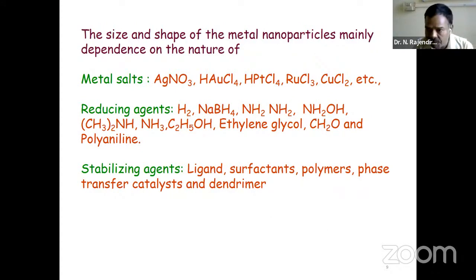And in the chemical methods, there are three constituents mainly required. That is the metal salt, reducing reagent, and stabilizing reagent. Normally, if you want to prepare silver nanoparticles, you have to take silver nitrate or silver chloride. For gold nanoparticles, auric chloride; for platinum, ruthenium, the respective metal salts we need to take. And we have to use the reducing reagent. Why? After the reduction of this metal, the oxidation state has to be reduced to zero oxidation state. For this purpose, we need to add a reducing reagent.